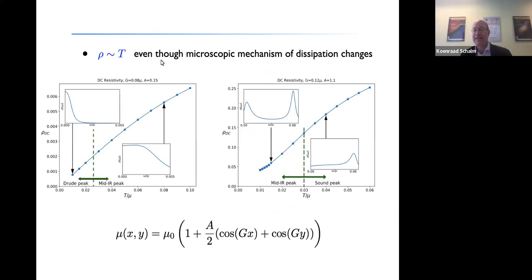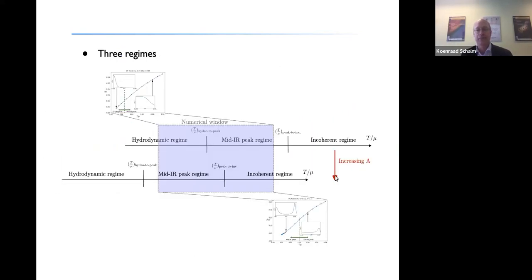But the main message that I want to tell you today is that even though this DC resistivity is almost linear in temperature, if you look more carefully, in particular if you look at the optical response, you see that the dissipative mechanism by which the energy is lost is very different throughout this regime where it stays linear. It starts at very low temperatures with an ordinary Drude behavior, but then it transitions to a regime where I have a mid-IR peak, and you can definitely not call this an ordinary Drude response anymore. And you can even go worse. There is an extra colliding peak regime as well, where the mid-IR peak collides with what we'll show is a sound peak in the system.